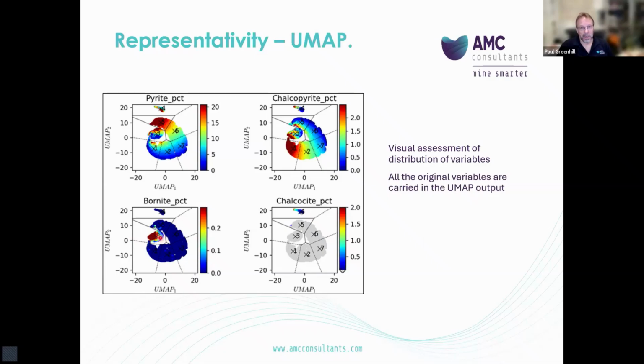And the hot colours are high grades in this instance, and you can see that the bornite, copper sulfide species, is isolated to this small island in the middle. Chalcopyrite exists in this region at the bottom corner of the horseshoe, and the only place where chalcocite appears within this UMAP projection is in this tiny island up to the top.